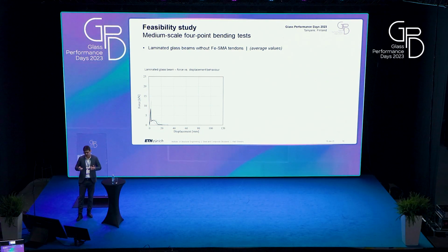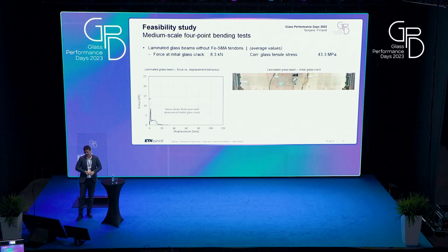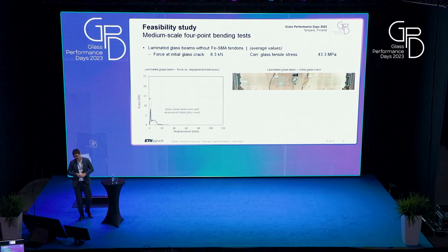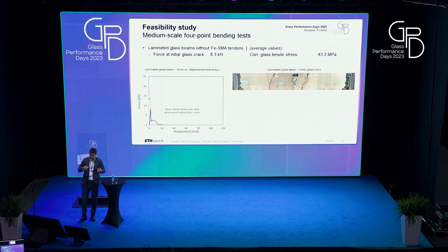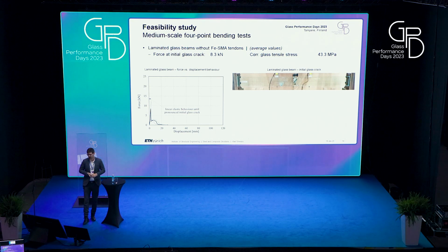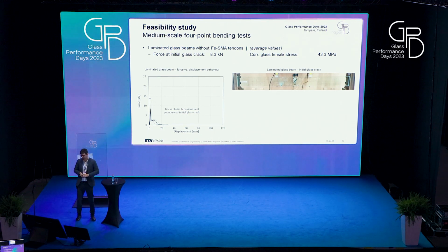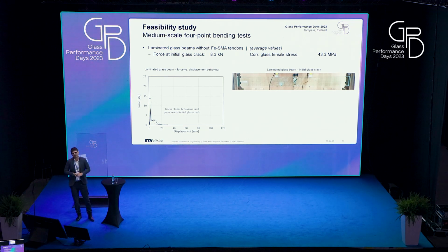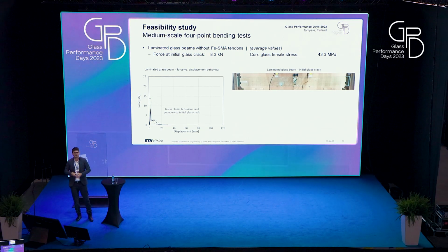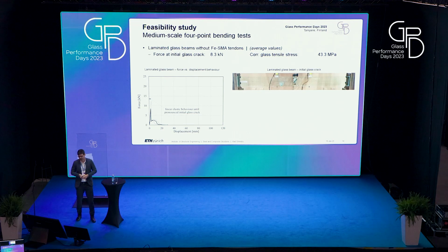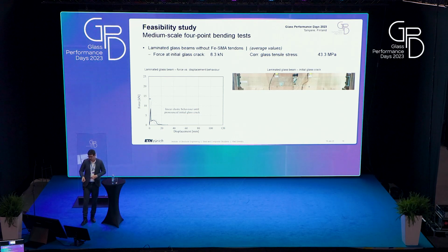If we look at the reference beams, we were able to reach a force at the initial glass crack of around 8 kilonewtons. The corresponding tensile stress that we measured with the strain gauges was around 43 megapascal, which is quite well in the range of the characteristic strength for annealed glass.